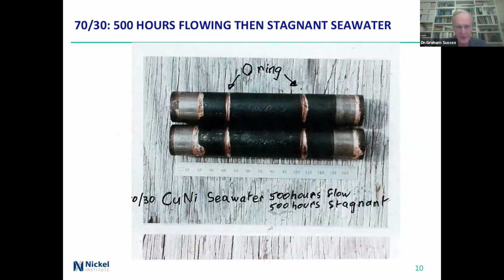This is looking at a 70-30 alloy, so there's more copper, less nickel. O-rings were put around these, and you can see where they've been clamped at the end, and the protruding bit at the end has been attacked. But the black color is basically not corroding, it's just copper oxide really. Underneath the gasket, you've got a bit of corrosion going on because it's not quite as good in a reducing environment. I have another picture of it, but I didn't think it showed particularly extra.